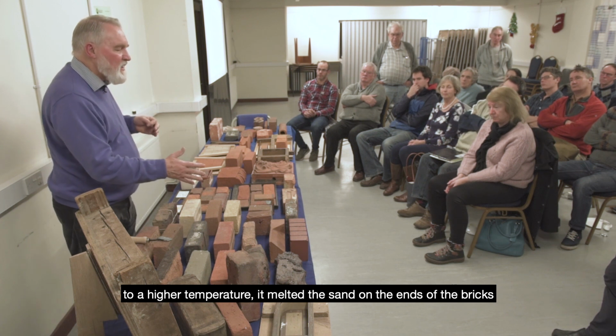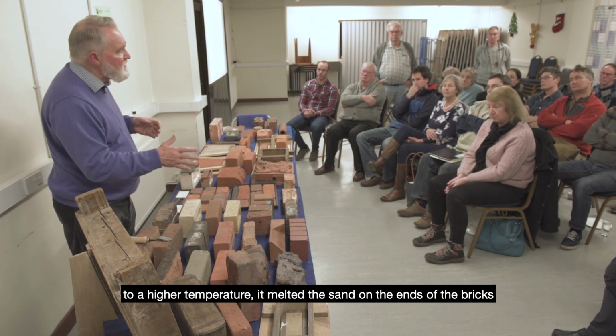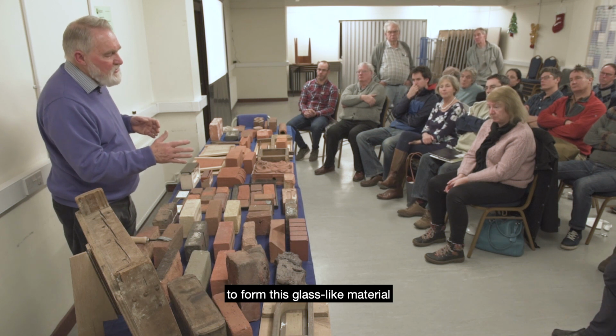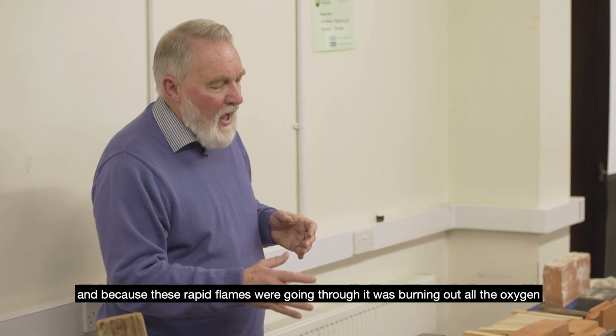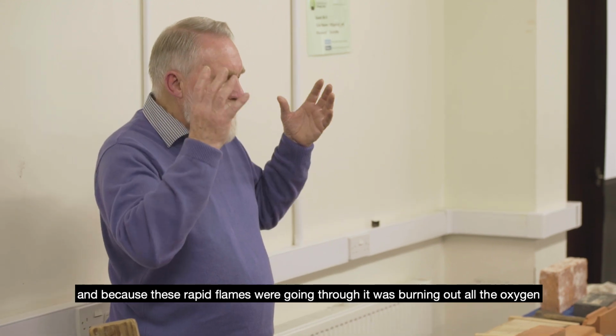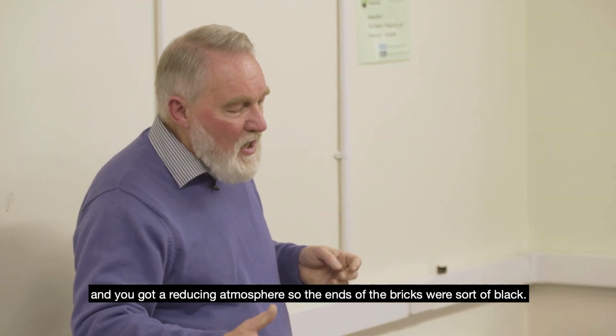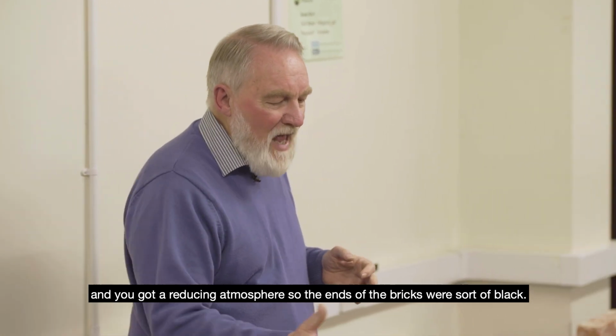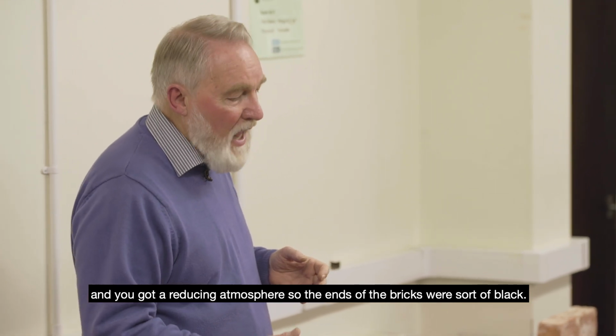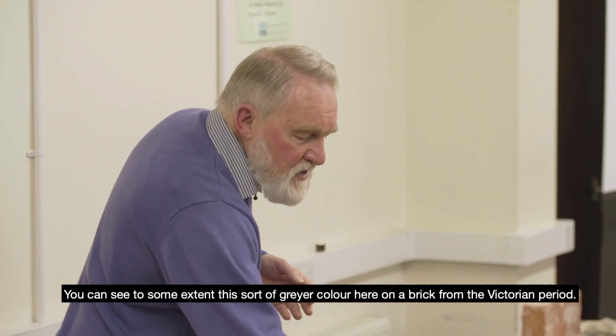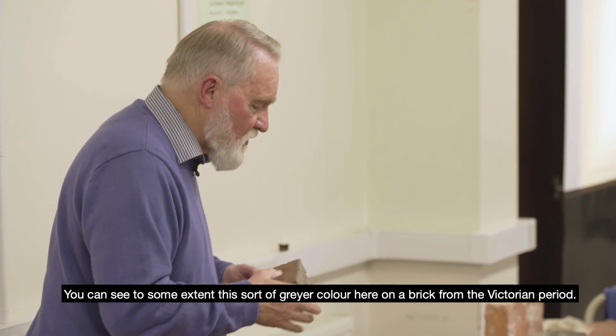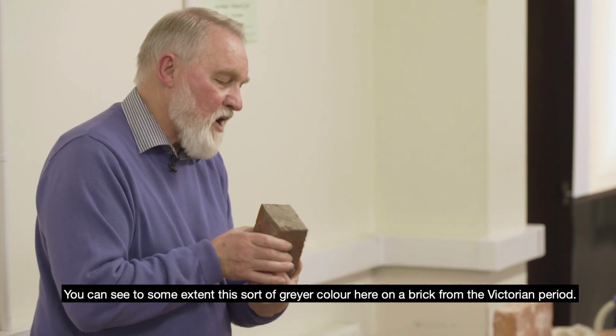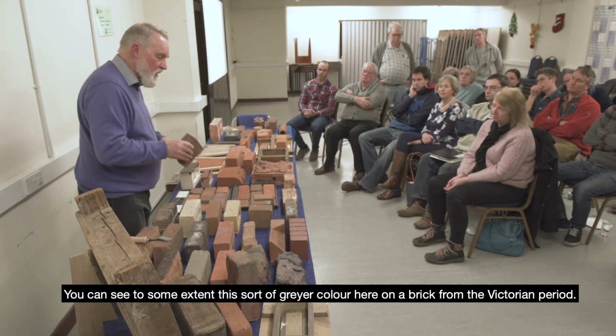It melted the sand on the ends of the bricks to form this glass-like material, and because these rapid flames were going through, it was burning out all the oxygen, and you got a reducing atmosphere, so the end of the bricks were black. You can see to some extent this grey colour here on a brick from the Victorian period.